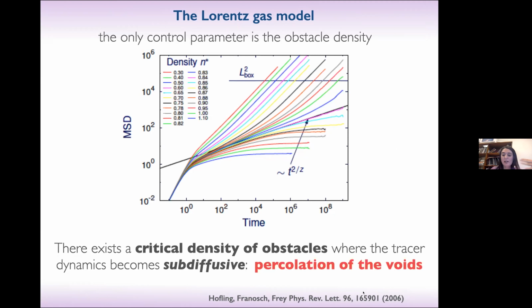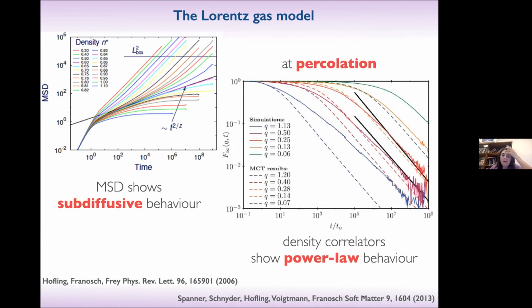The Franosch group, Frey, Hoffling, and so on, did a lot of simulation on that. In particular, now the MSD shows subdiffusive behavior, but the density correlators studied in this paper show not a logarithmic behavior like we saw before, but rather a power law behavior close to this transition. Okay, so a different behavior than the one predicted by MCT for standard glasses. So this is another transition.